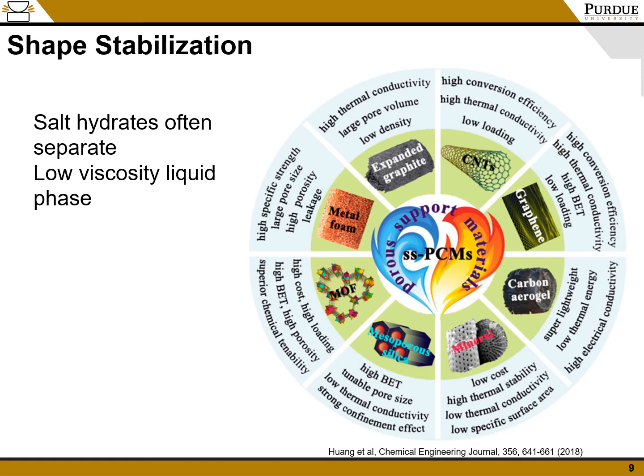Metal foams and metal organic frameworks, while both having high specific strengths and high loading factors, can often lead to leakage, and because of the corrosive nature of inorganic PCMs, they aren't quite valid for these materials. Carbon nanotubes and graphene have very high thermal conductivities, but they have very low loadings, so you can't add as much of the PCMs into them as you would maybe like. Two of the most promising ones for inorganic PCMs currently looked at are expanded graphite and porous silica matrices. Expanded graphite has high thermal conductivity and low density without very much problems, and silica has high specific surface areas and tunable pore sizes, but they don't quite add into the thermal conductivity like expanded graphite does.